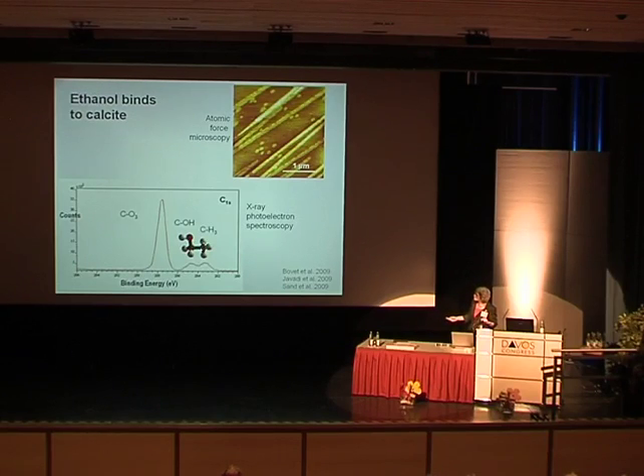Ethanol is C2 with 3 H's there, 2 H's here, and an OH. Ethanol is interesting because it's the most simple OH organic material that we can use to experiment with. Water is also a very simple OH, but it doesn't have the organic component. So we exposed some calcite to ethanol, and we saw a very strange behavior.